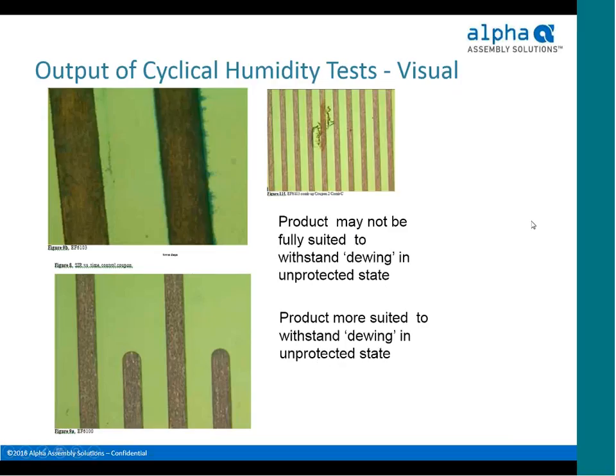There's also a visual aspect of this as well. Obviously, you don't want to see what we see on top right, actual visible evidence of dendrites. On the top left, that's a good indication that although the unit may have passed, this would be one where you would tend to want to apply conformal coating as a protective measure. You see some beginning of corrosion due to the high levels of humidity and near condensation. Bottom left condition, that's definitely what you want, where you see no effects on the copper pattern, even in that environmental test chamber.